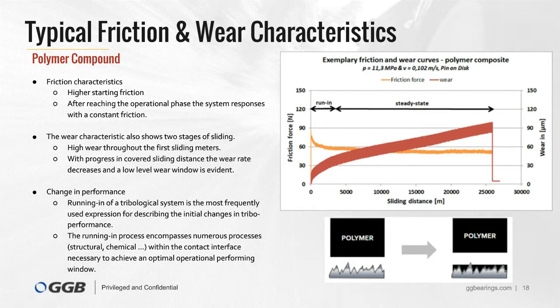We can also call this phase the operational phase, which remains during the entire test duration. The wear characteristic can also be divided into two stages. The first phase is characterized by a higher wear curve slope. The wear rate decreases until the operational performing window is reached, during which we find a linear wear characteristic.